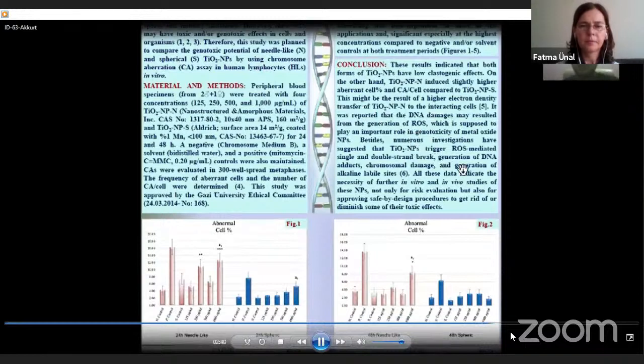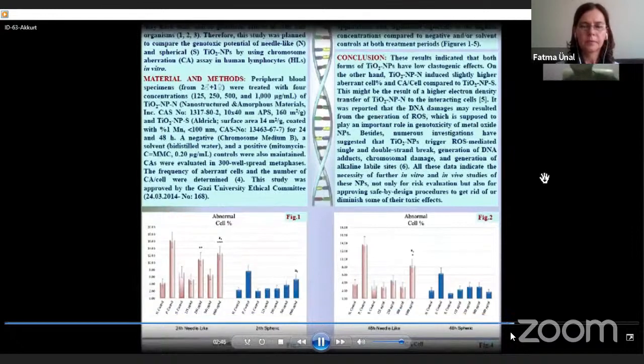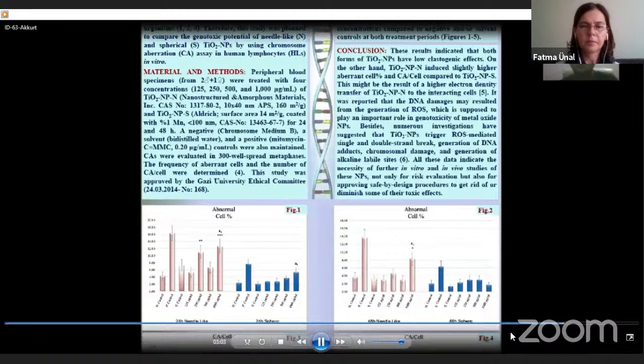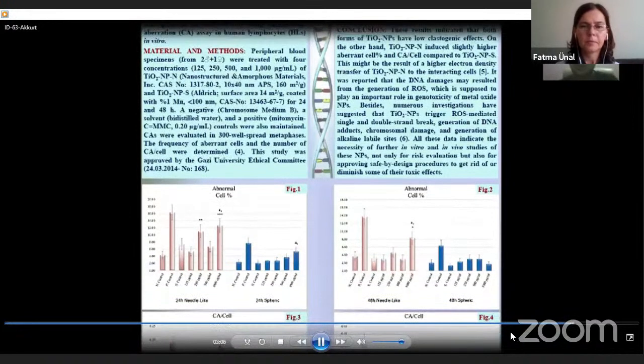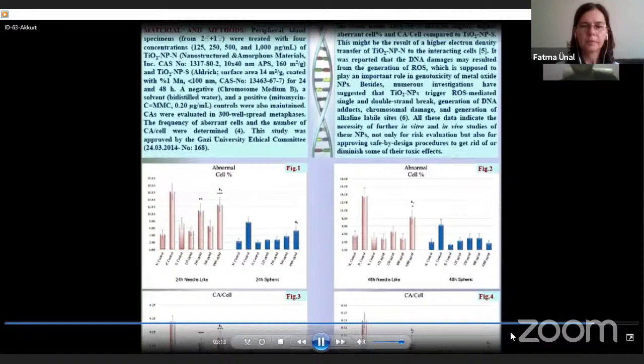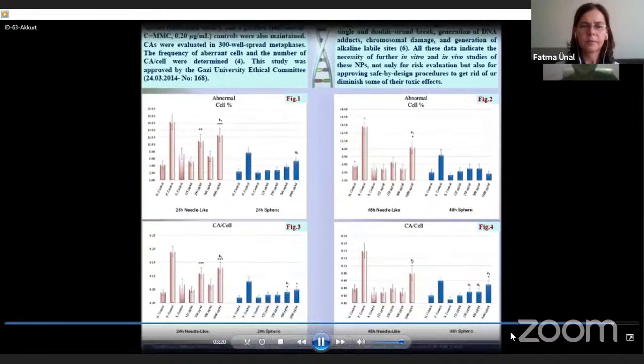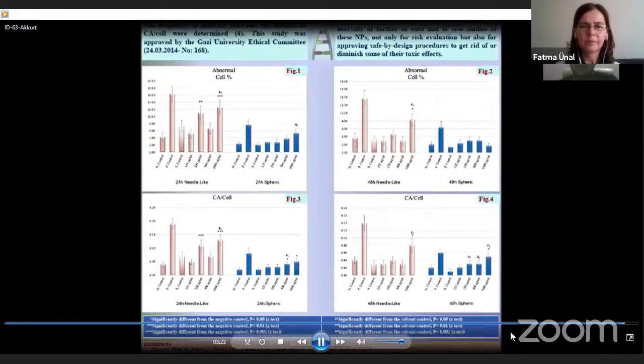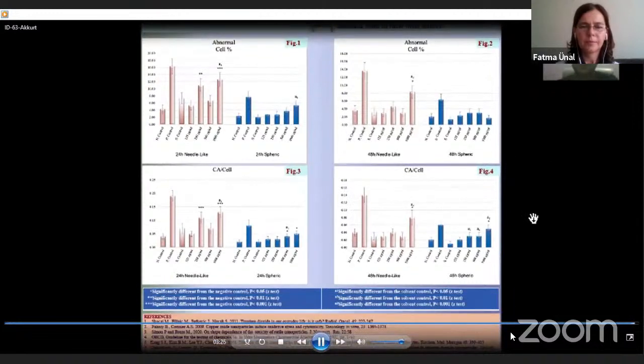It was reported that DNA damage may result from the generation of reactive oxygen species, which is supposed to play an important role in the genotoxicity of metal oxide nanoparticles. Besides, numerous investigations have suggested that titanium dioxide nanoparticles trigger reactive oxygen species-mediated single and double-strand breaks, generation of DNA adducts, chromosomal damage, and generation of alkali labile sites. All these data indicate the necessity of further in vitro and in vivo studies of these nanoparticles, not only for risk evaluation but also for approving safe-by-design procedures to get rid of or diminish some of their toxic effects. Also, you can see the results here graphically. Thank you for listening. Have a nice day.